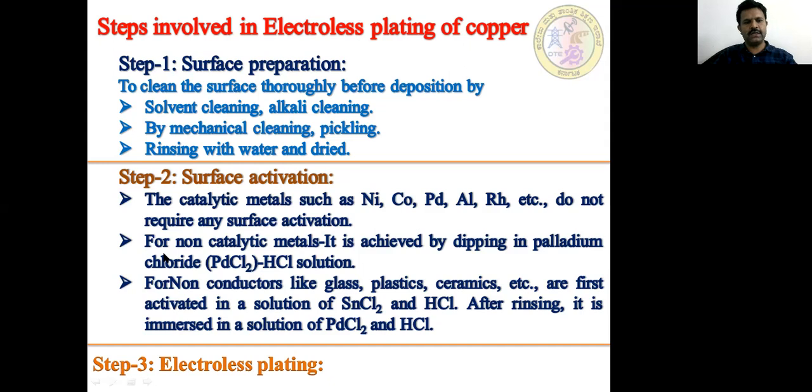If the substrate is a non-catalytic metal, then the surface is activated by dipping in palladium chloride HCl solution. Here palladium is a catalytic metal. By dipping in it, we can activate the surface.